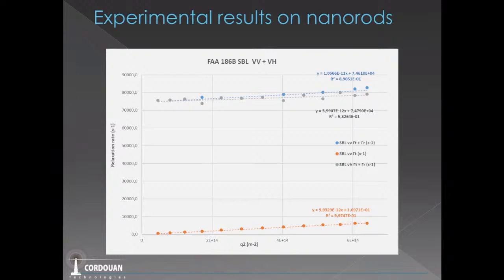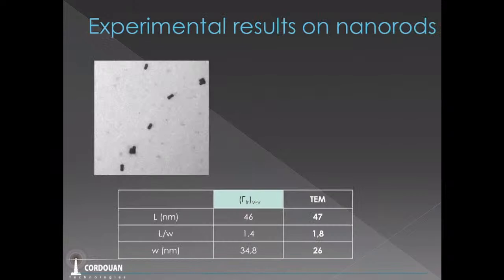For example, if the second line here is going through zero, which sometimes you can find, in that case the two populations that you see are really two spherical populations. If it's an anisotropic population, you need to have parallel lines here. That's why this graph is really important, because you can get a lot of information about what you are looking at. Even with this graph, you can see if you have a mix of isotropic, so spherical, nanoparticles and anisotropic nanoparticles.